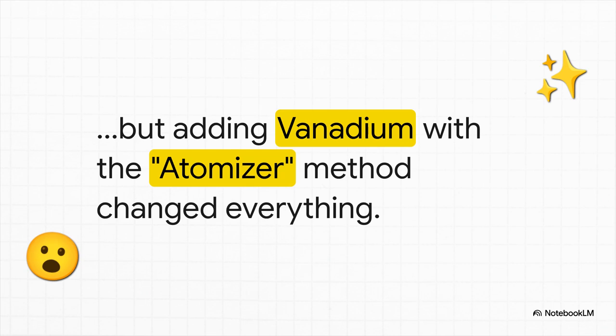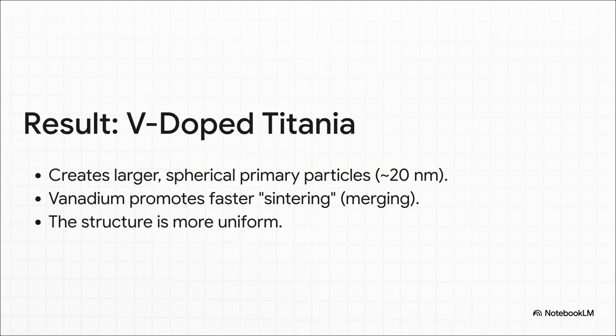But then, when they switched to the atomizer method and sprayed in that vanadium dopant, everything changed. This one simple change to the recipe completely transformed the material they ended up with. With this new method, the primary particles were suddenly twice as big, about 20 nanometers, and they were much, much more spherical. It turns out that adding the vanadium this way actually sped up that sintering process, encouraging the particles to merge more completely into these rounder, more uniform shapes.